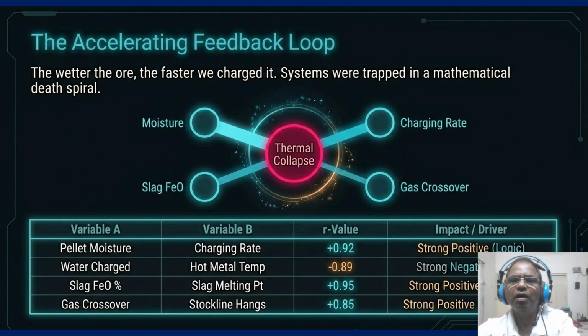Now check the R values in the table. Pellet moisture and charging rate have a 0.92 positive correlation. The wetter the ore, the faster the automation charges it. Simultaneously, water charge and hot metal temperature had a 0.89 negative correlation, a massive energy drain.